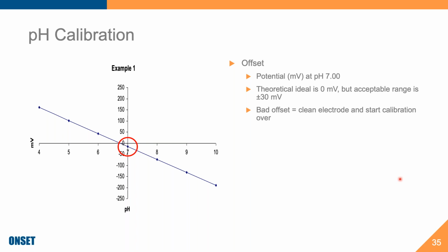Theoretically, you want your offset to be 0 millivolts. You want your pH electrode at room temperature to be neutral, actually 0. And if you have your potential for your offset plus or minus 30 millivolts, if it's within that, then that's an acceptable range. But anything outside of that, I would recommend either cleaning your electrode or starting the calibration over.